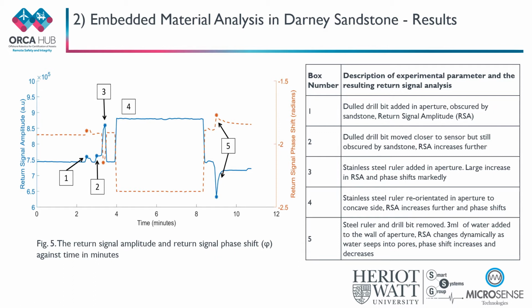With the stainless steel ruler reorientated in the aperture with the concave side facing the antenna, the return signal amplitude increases further and phase shifts significantly also. Before point 5, the ruler and dull drill bit are then removed from the aperture, where enough time is given to allow the baseline to re-establish itself.